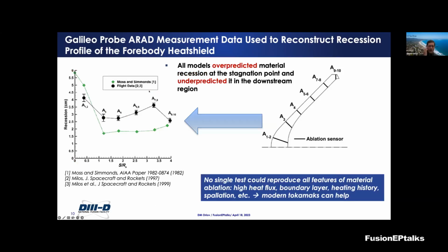But when we got the data from those sensors back on Earth, shown in black dots here on the left figure, and when we compared that to the simulations, it appeared that the recession of the thermal heat shield material at the nose was overestimated, and the loss of material at the back was severely underestimated. This is from Moss and Simmons, 1982 paper.